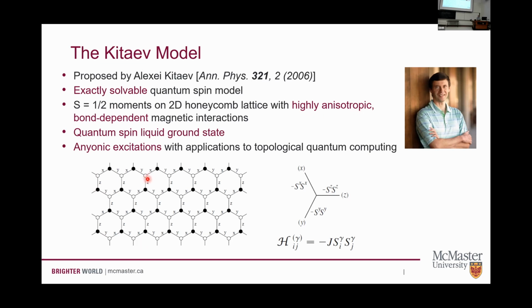So if you imagine sitting on one of these honeycomb sites, you can go off in 3 different directions. Each of these would have a different strength. And because of this exchange frustration, we don't get normal magnetic order setting in. Instead, we get what's called a quantum spin liquid. This is a disordered quantum state where the spins are interacting with each other. They have long-range entanglement, but they never order. And so they have unusual topological properties, things like Majorana fermions and anyonic excitations. These can be of interest to people looking to design topological quantum computers because they provide a topologically stabilized way of cutting down on quantum errors.